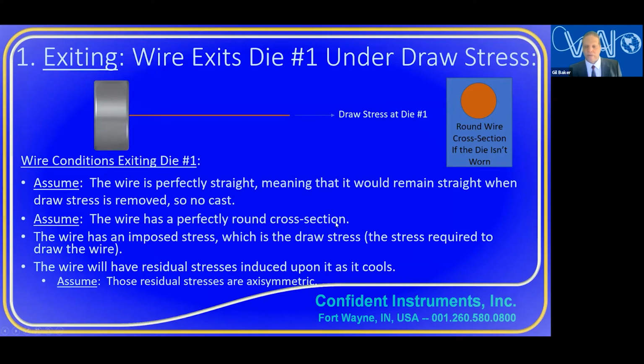The wire has a perfectly round cross section. Again, we're going to assume that the die's bearing is perfectly round and the wire comes out perfectly round. The wire has imposed stress, so this is the stress imposed upon it. That's an important part. And that's the draw stress. The wire will have residual stresses induced upon it when it cools. And for now, we're going to assume those residual stresses are axisymmetric. So axisymmetric is typically how you think of a round wire with a round cross section. I could just call it symmetric, but we're going to talk about asymmetric later.